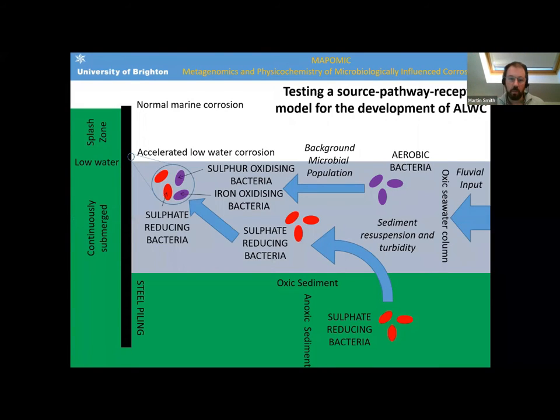So if I turn back to MAPOMIC, what we first set out to test, the phenomenon of accelerated low water corrosion was well recognized. What wasn't known is where the causative bacteria were coming from. So the initial hypothesis, just taking a simple source pathway receptor model, is that we've got sulfate reducing bacteria that are responsible for sulfate reduction and pyrite generation in the bed sediment that are resuspended. They have a limited survival time in the water column. And during that survival time, they're colonizing anaerobic microenvironments on the steelwork caused by macrobiofilms, algae, mollusks, and so on. And we've got potential colonies of both sulfate reducing and oxidizing bacteria. So this was the starting idea.